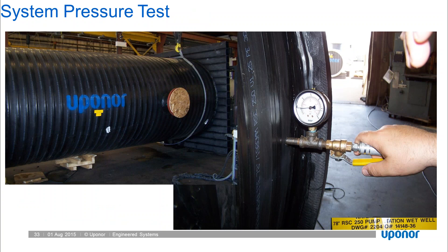Here you can see a snapshot of a pressure test. Unique to Weholite, the annular space is a helically-wound annular space continuous throughout the structure. We can pressure test any slab—either base or top slab—or any penetration through the vessel. We pressurize the annular space to about 5 psi. If it holds pressure, we have a high-quality weld and a completely watertight system prior to shipment. This is advantageous when a 24-hour drawdown requirement exists, as we know for 100% certainty there will be no leakage in the field after backfilling.